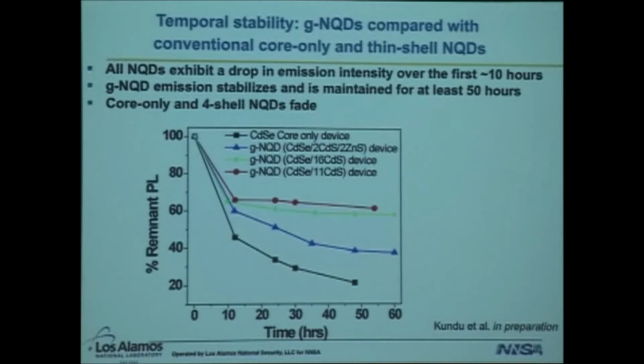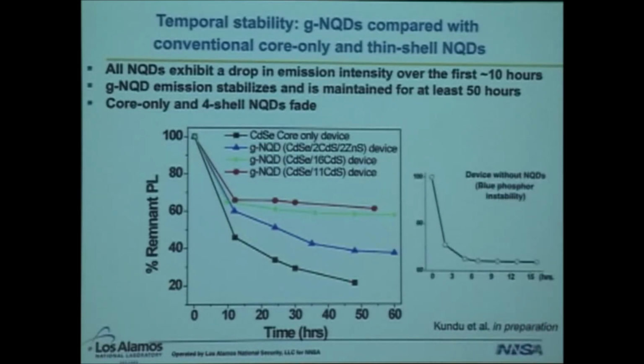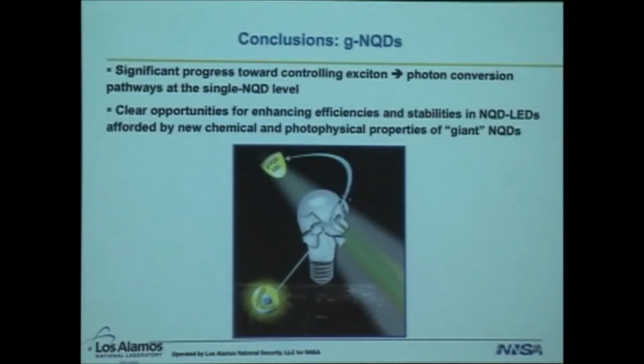And we also find that stability, we're looking at about 50 to 60 hours, of the thicker shell systems is significantly improved compared to the thinner shell or the core-only systems. This initial drop actually has to do with the EL phosphor and not with the dots at all. So, okay, conclusions in terms of giant dots. I think we've demonstrated that we've made significant progress towards controlling exciton-to-photon conversion pathways at the single particle level, and that there's now clear opportunities for enhancing the efficiencies and the stabilities in NQD-based LEDs.